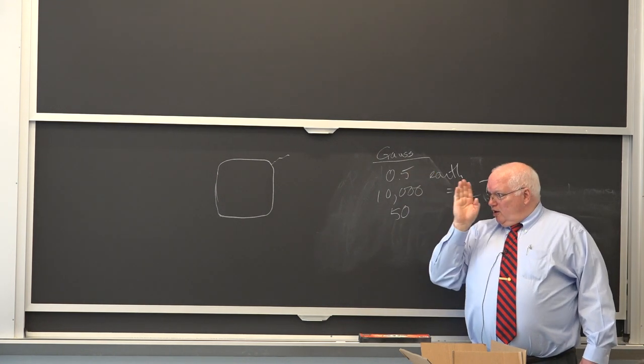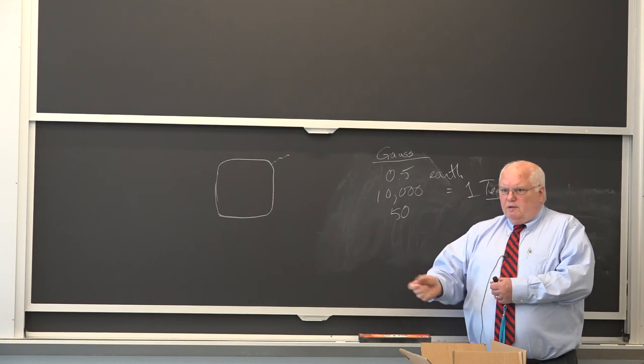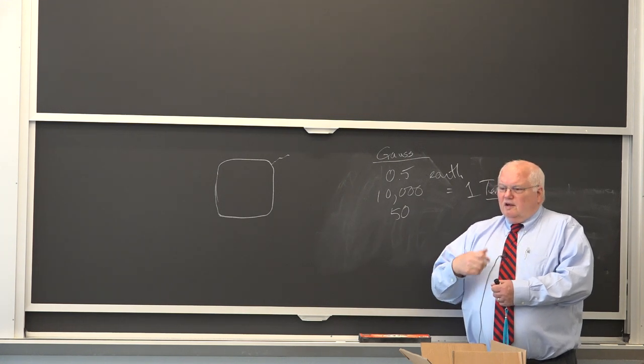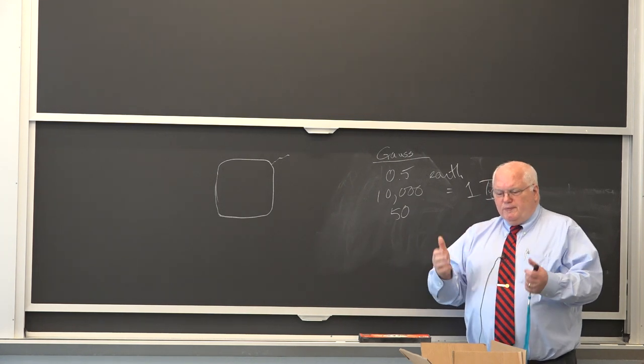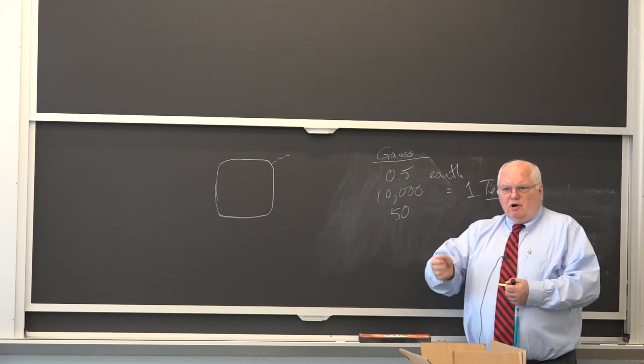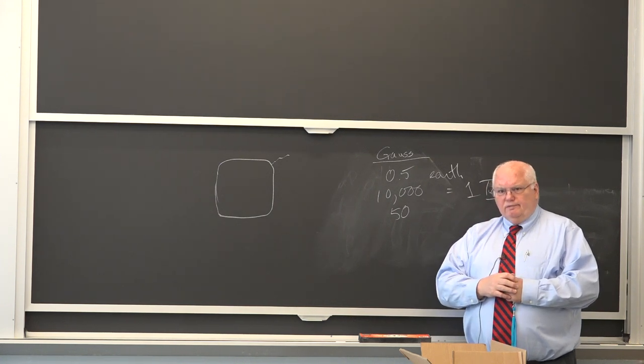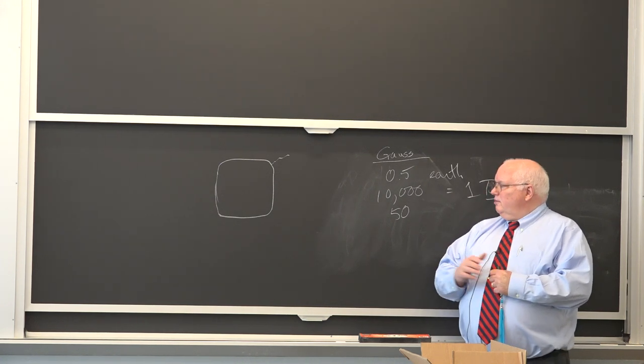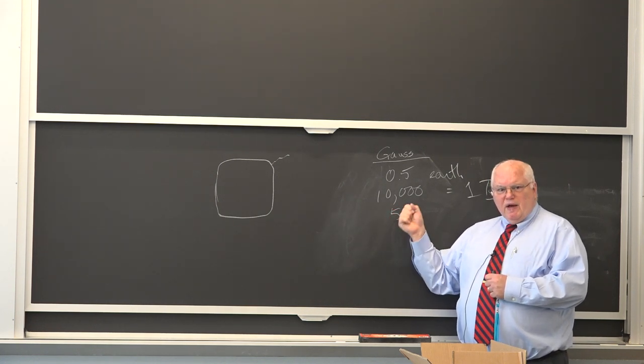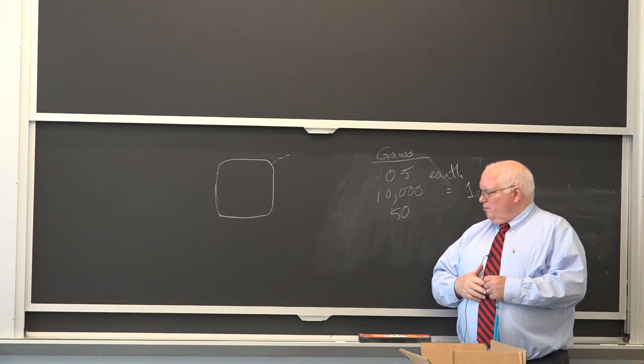You ever seen someone take a steel rod and pound on it when it's aligned with the Earth's magnetic field? When you vibrate it, you can get those magnetic domains to line up, and you can magnetize a bar of steel by hitting it with a hammer when it's parallel with the Earth's magnetic field, okay? So in any case, 50 Gauss is what the self-magnetization of steel would be that would cause problems with magnetic arc blow and stuff.